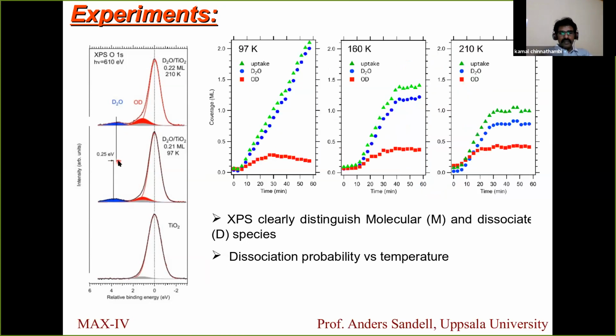And also they perform the growth at three different temperatures. They perform the uptake of these water molecules. So you can see that at a very low temperature, 97 Kelvin, there is no limit for adsorption, because the ice at 97 Kelvin under ultra high vacuum is quite stable. When you put this on the surface, it diffuses and then spreads out. So there is no limit to it. But when you come to 160 and then 210 Kelvin, there is a saturation. After some time they get saturated.